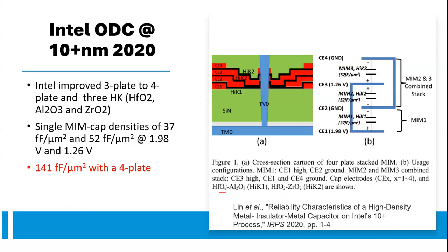Hafnium oxide is your baseline, so you use that. And then you use aluminum oxide probably because it has the lowest leakage. And zirconium oxide, you use it because it has a lower crystallization temperature. And you mix them, and then you see what comes out, right? I think they did a lot of DOE for that. Just like the high-K metal gate, right? They had a lot of metal gate options. Eventually, they found out aluminum works best. It's just by experiment. Well, that's the beauty of Intel.